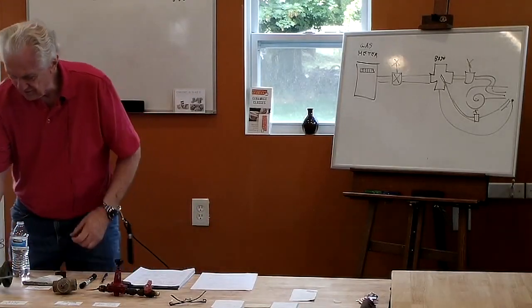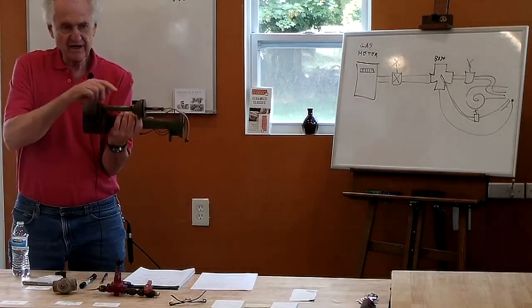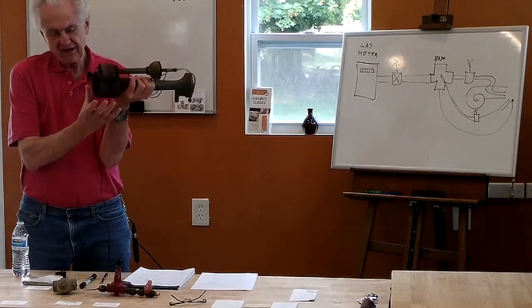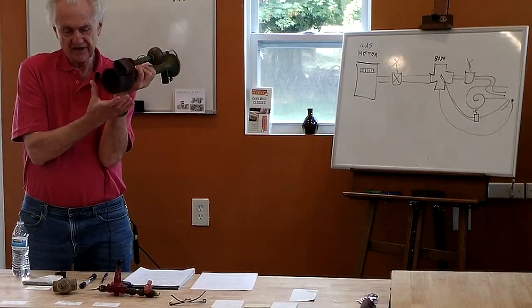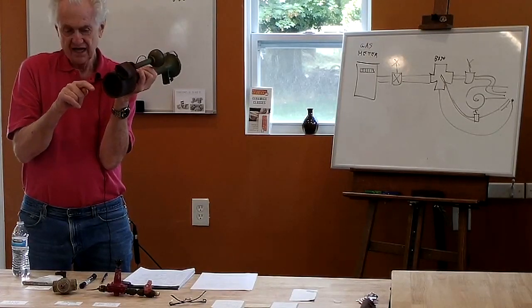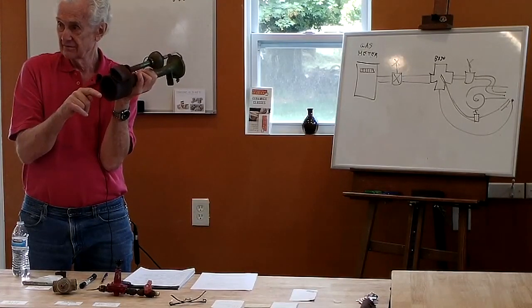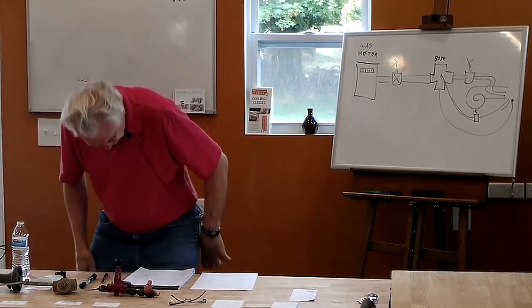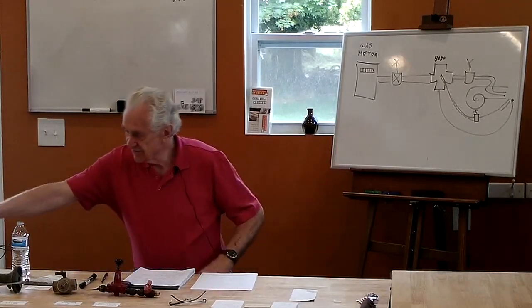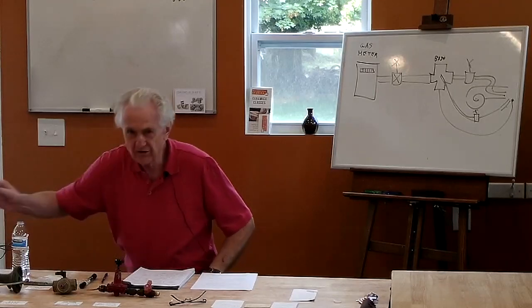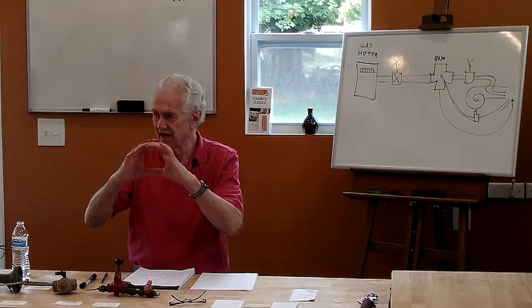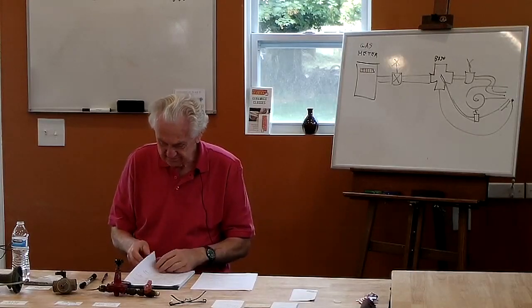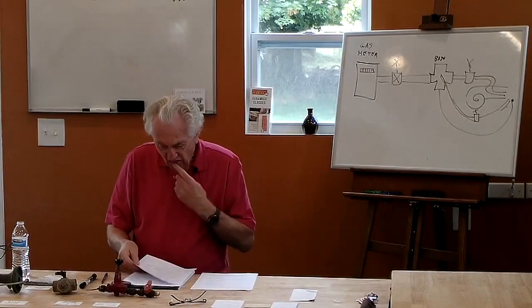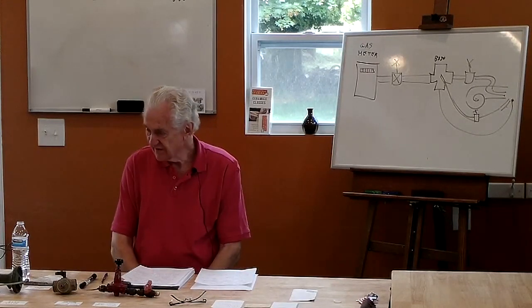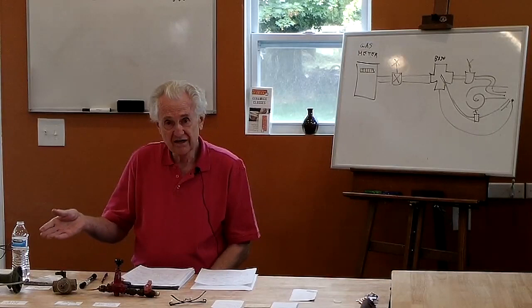That additional air is called secondary air. So when I set up this burner on a kiln, I have air coming into the burner through here, and I also leave a space around the burner head where it goes into the kiln, where additional air can be drawn in and mixed with the gas. That's the secondary air. And so with a Venturi burner, I need secondary air. So I need a space or a place around the burners for air to be able to get in. I don't just seal that burner head up tight to the kiln. And then if I need secondary air, I need some way to pull it in, so I need a chimney.